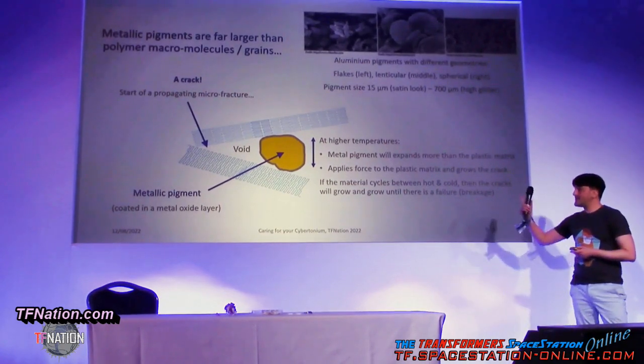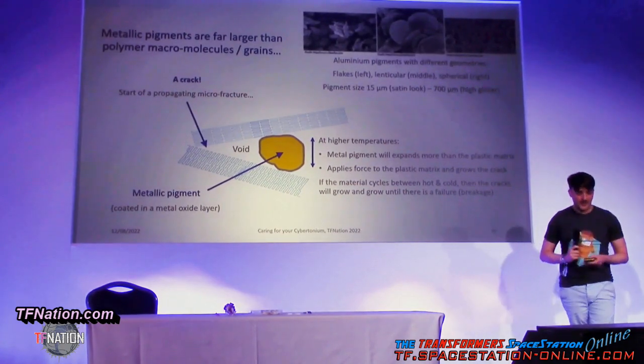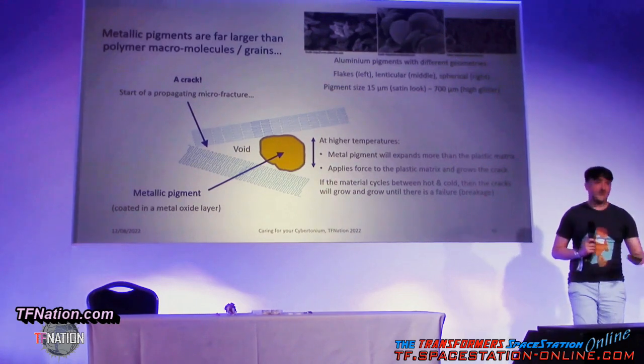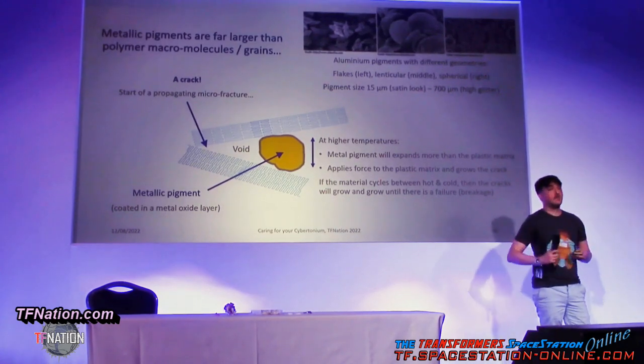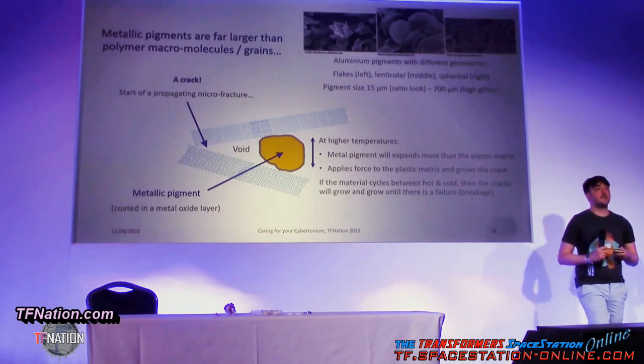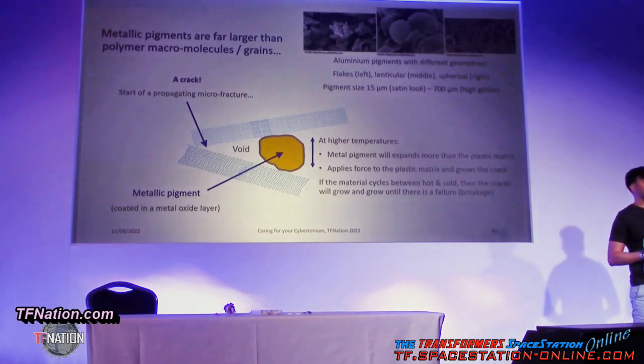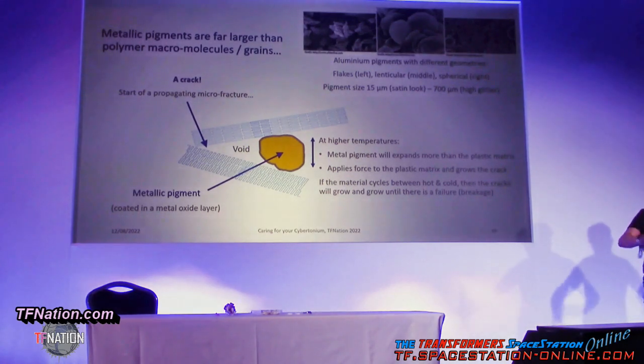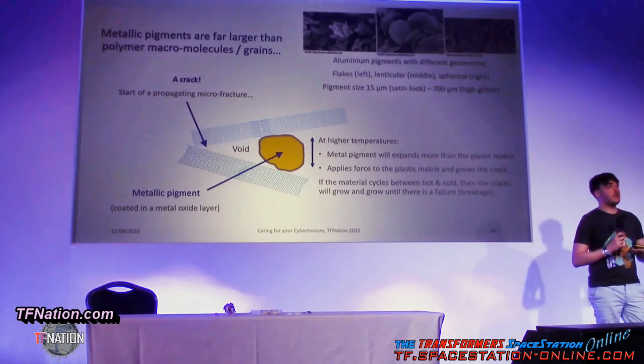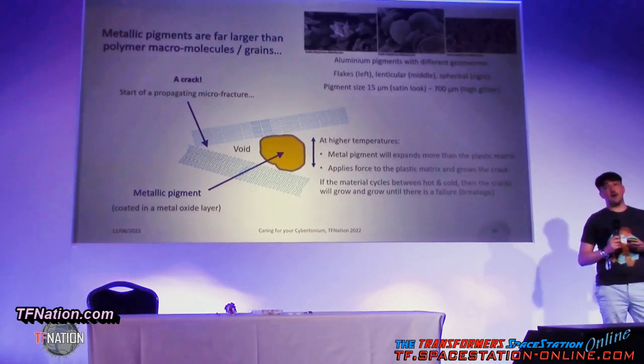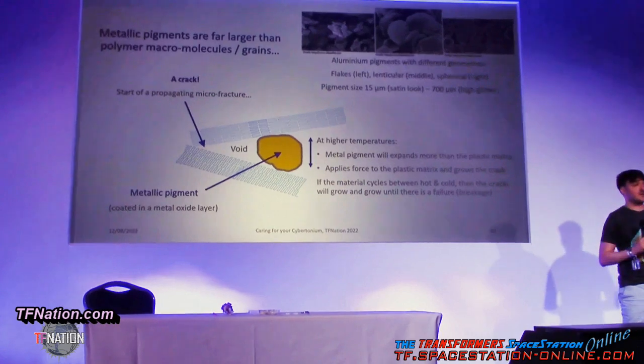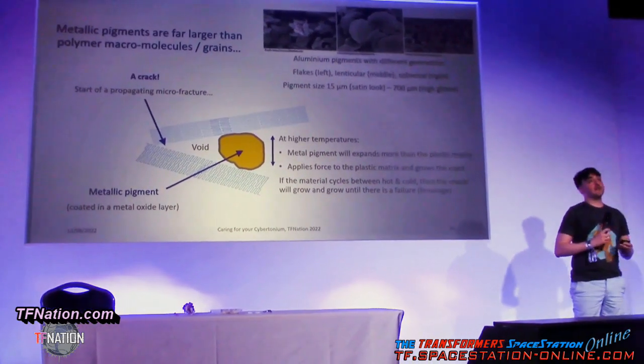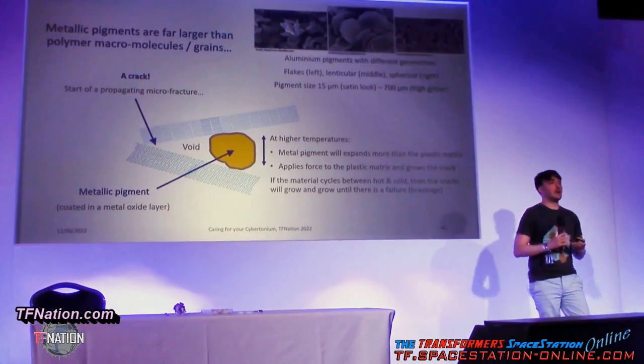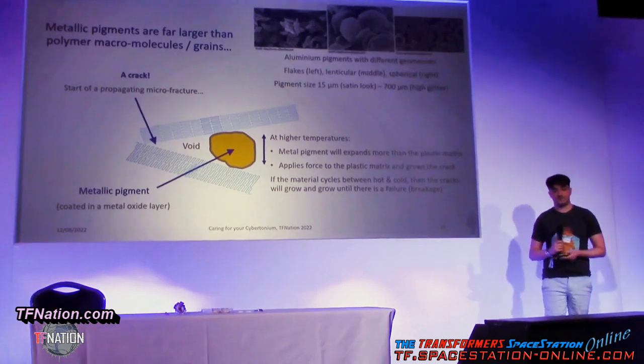And apologies, I have got this in the text the wrong way. The coefficients of thermal expansion are actually the opposite. Plastic does expand with heat about 4 times or so more than metal. So if you had 1 meter of aluminium, it will expand by roughly 20 microns per degree Celsius, whereas ABS will expand about 80 microns per degree Celsius.